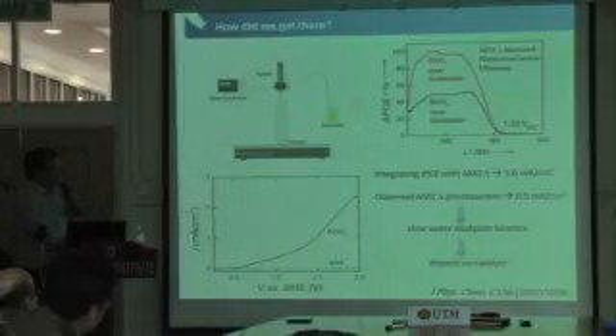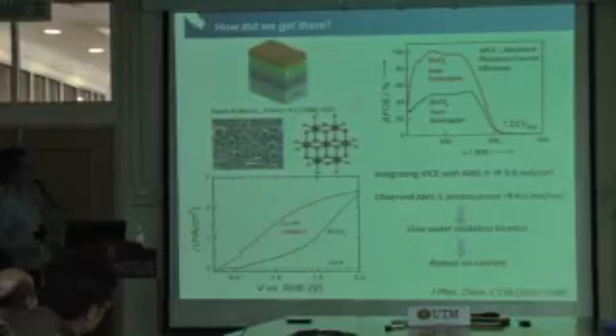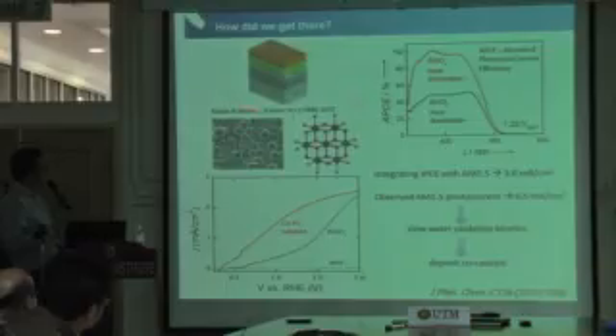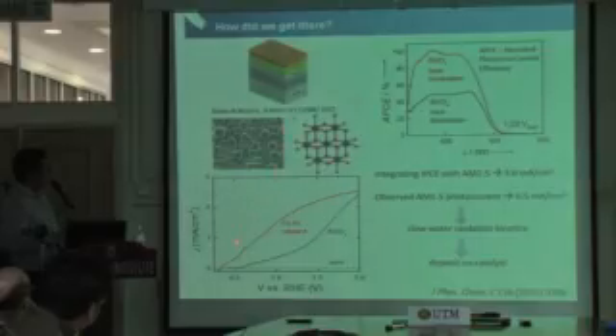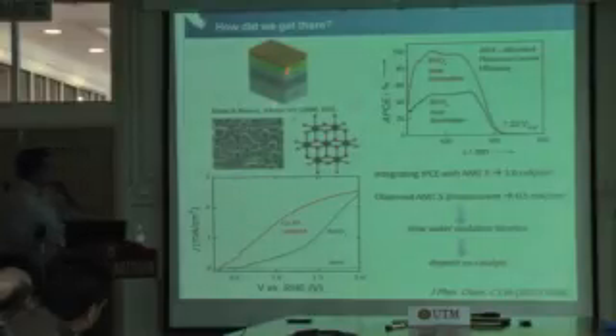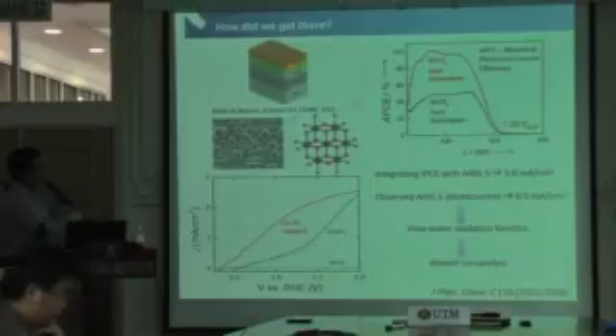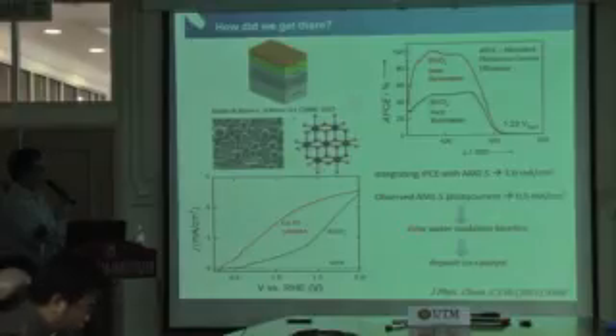So the obvious solution at that point is to deposit a co-catalyst, a known water oxidation catalyst, on top of the bismuth vanadate. And we chose this cobalt phosphate, which was developed at MIT in Nocera's lab, though he's at Harvard now. We just put it on top of our bismuth vanadate, and as soon as we did that, the photocurrent actually improved quite significantly, right? So we thought it was improving the water oxidation kinetics, but towards the end of the talk, I will also discuss the role of this cobalt phosphate.